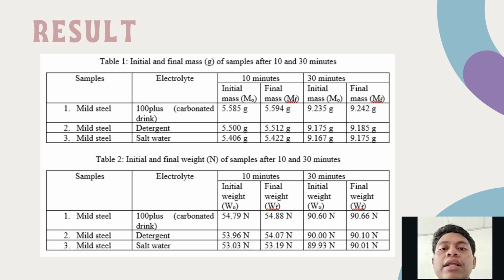with different electrolytes. Sample 1 is 100 plus carbonated, which for 10 minutes initial mass is 5.585 gram, final mass 5.594 gram, for 30 minutes 9.235 gram, and 9.242 gram for final mass. For the second sample, the electrolyte is detergent, where initial mass for 10 minutes is 5.5 gram and 5.512 gram for the final mass, and for 30 minutes 9.175 gram and 9.185 gram for the final mass. And the last electrolyte is salt water, where for 10 minutes initial mass is 5.406 gram and 5.422 gram for final mass, and for 30 minutes 9.167 gram and 9.175 gram for final mass.